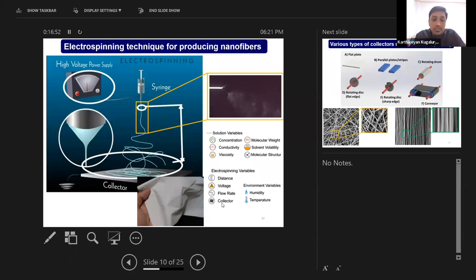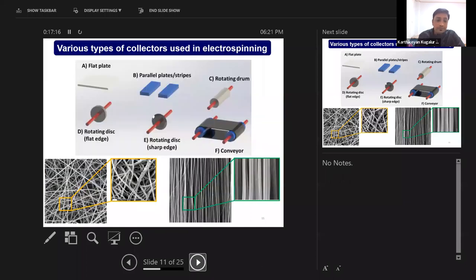So our ultimate aim is to produce a nanofiber diameter that is very small. Then only it has so many advantages. As I said, electrospinning is one of the efficient techniques for producing nanofibers. The nanofiber should be approximately in the size of 100 to 200 nanometers, which is used for the catalyst layer for the fuel cells.